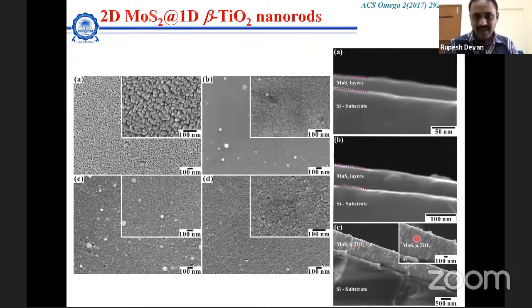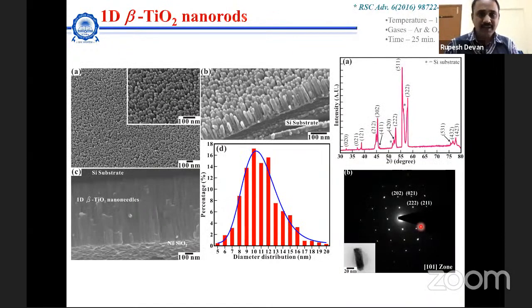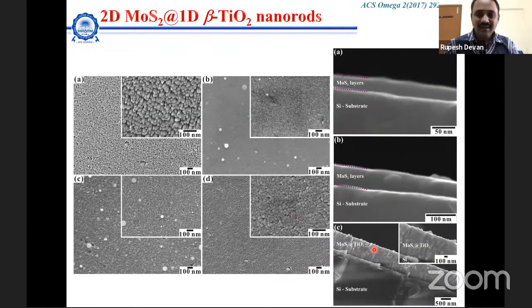If you look at the earlier images, these nanorods were quite opaque. They were individual, independent nanorods. But once you coat the MoS2, they become a little bit compact, and the thickness increased with the change in parameters during this deposition. The next challenge was, does the TiO2 remain intact? That means, no suboxide phase forms. So we checked it with XPS.